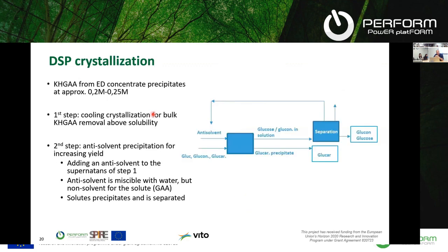The next step in the DSP would be a crystallization step. So from the electrodialysis, we get a concentrated mixture of acids. And the first step there would be a cooling crystallization, where some of the potassium monoglucarate in this case would crystallize already. To enhance crystallization, to actually lower the solubility in a sense, an anti-solvent was also used to decrease the solubility and increase the crystallization even more.